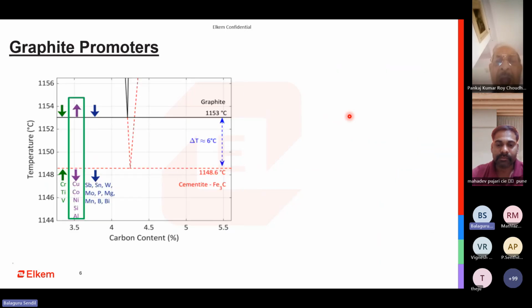I would like to first start with graphite promoters. So what do we mean by graphite promoters? These are elements which can ensure that the carbon we have in our metal, either 3.5, 3.6 or 3.2 in the case of gray iron, will come out as graphite and not as a carbide.